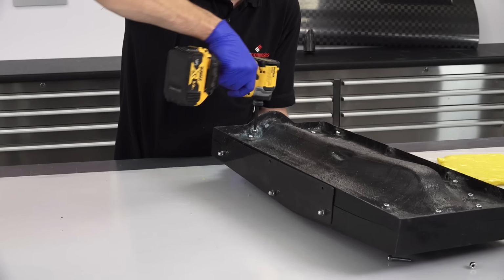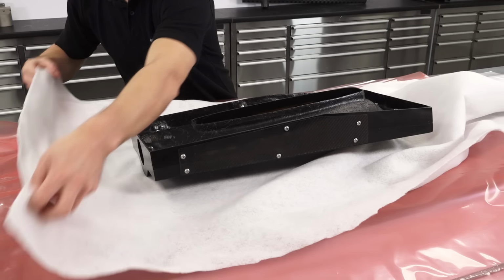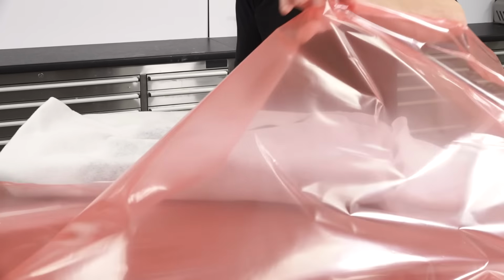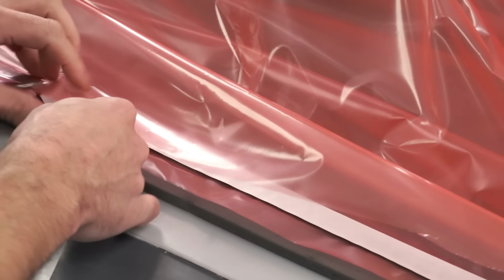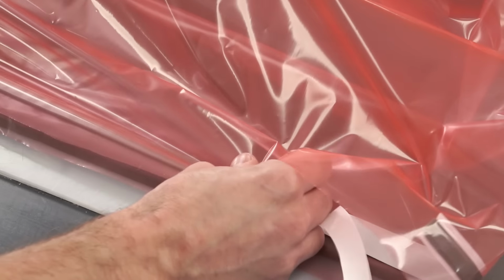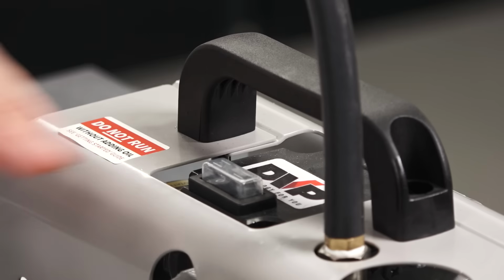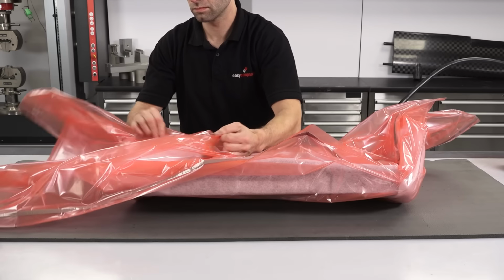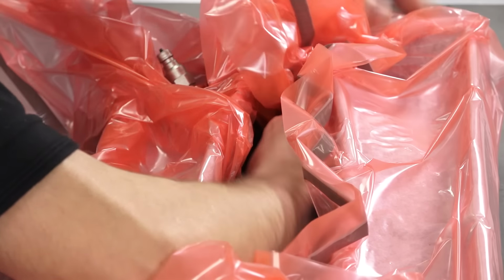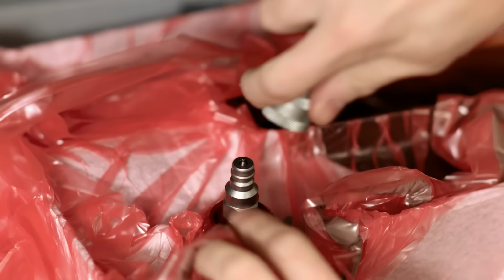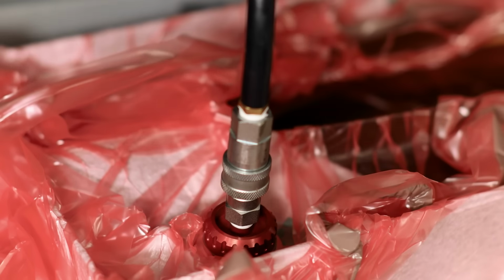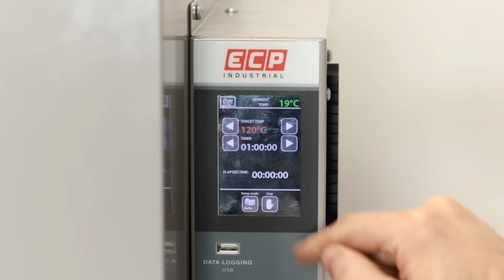The next step is to vacuum bag this to ensure full consolidation. Although not absolutely necessary, vacuum bagging the intensifier will help to reduce any voids in it and also smoothens and blends the surface further. Ensure that all of the silicone is covered in release film, then wrap this with breather fabric and vacuum bag in the conventional way. Check the Intensil datasheet for alternative cure cycles, but here I'm curing under full vacuum for 1 hour at 120 degrees C.